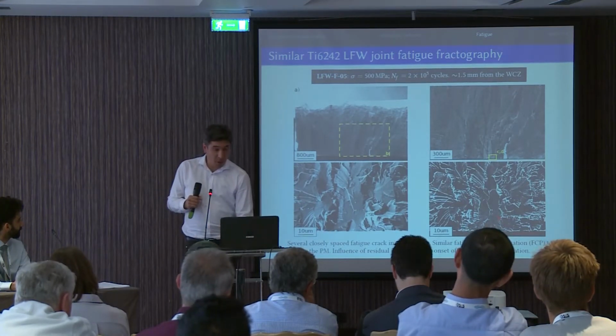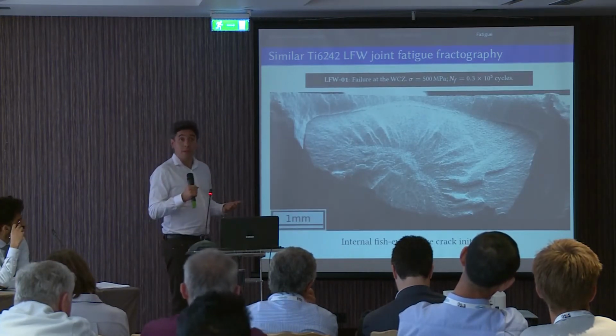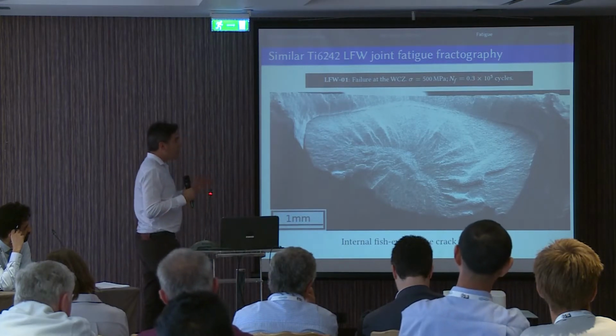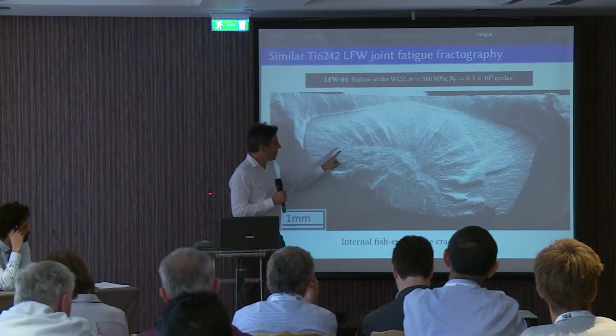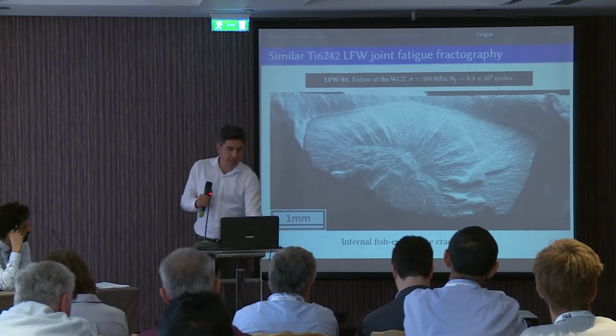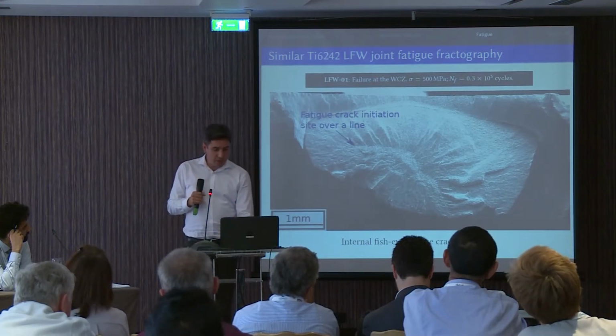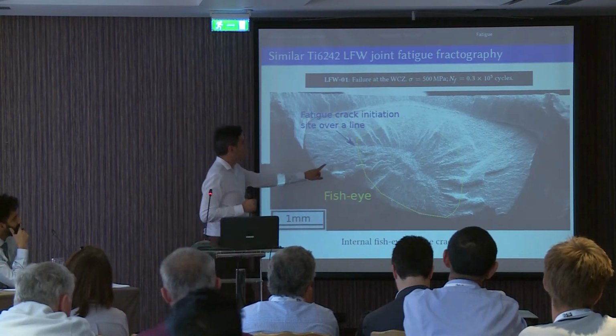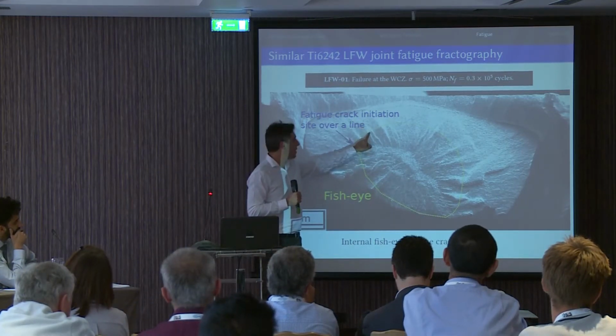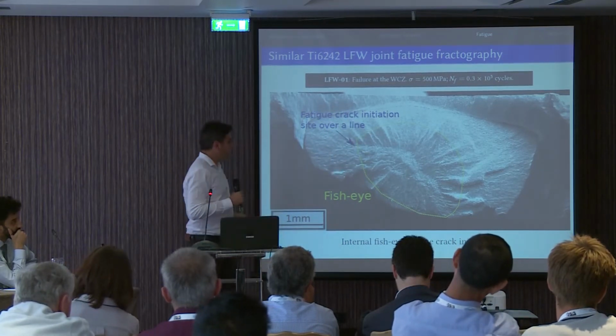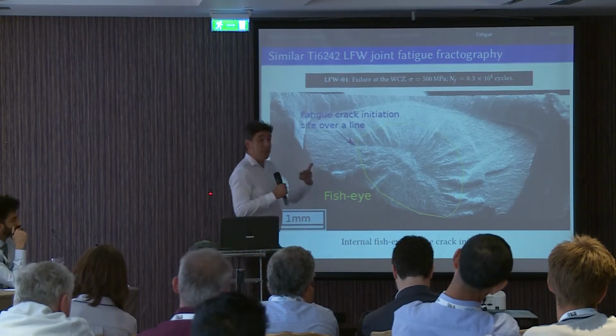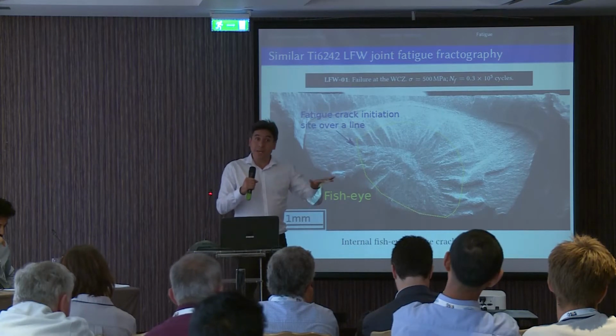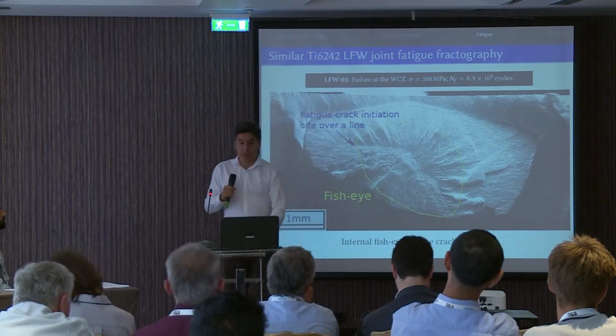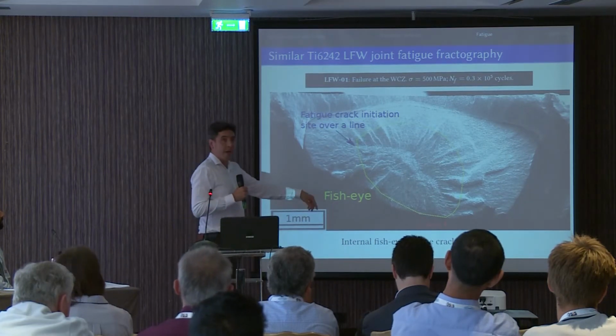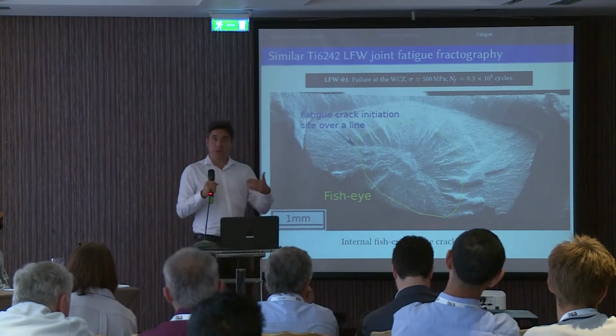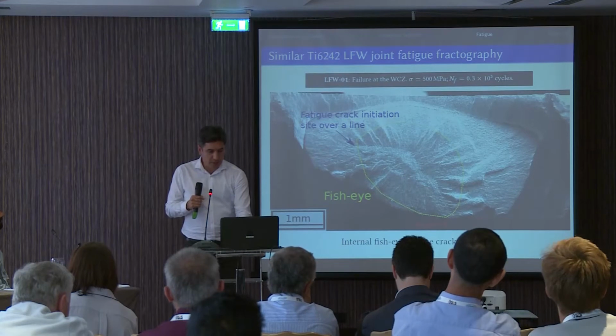fatigue propagation. Now we're going to look at the short life specimen, the one that had a very short life, and we can see that the fatigue ridges converge to a line in the center. So we have the fatigue crack initiation site over a line, and if you pay attention, you can see that the roughness of the fatigue ridges is smooth until this line, and then it becomes rougher. How can we explain this? We can imagine that, given it is internal, the crack propagation happens in vacuum until it reaches the specimen surface. And there, the air can enter, and it changes the environmental conditions. So now we have the propagation in air conditions.